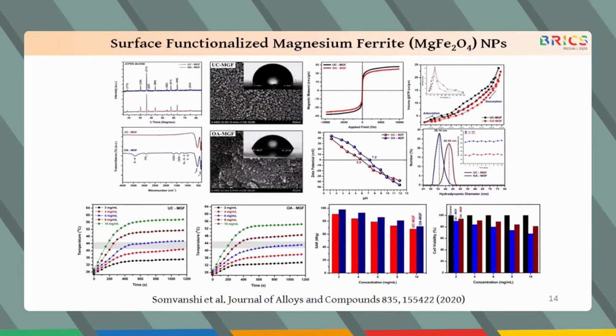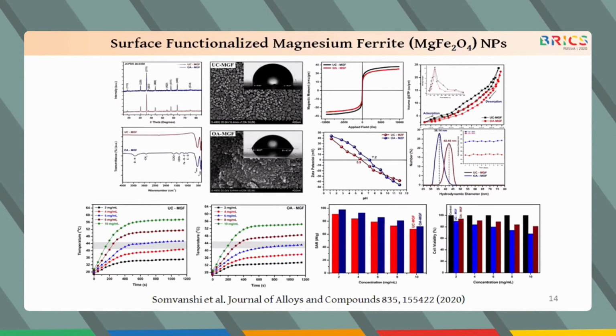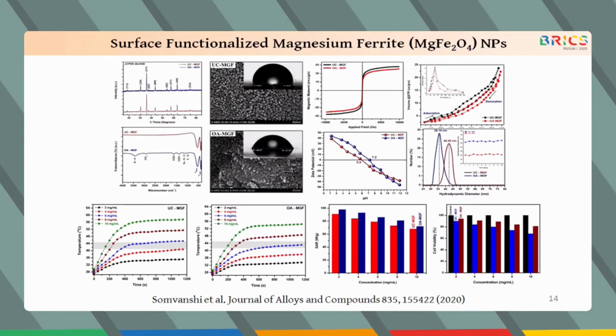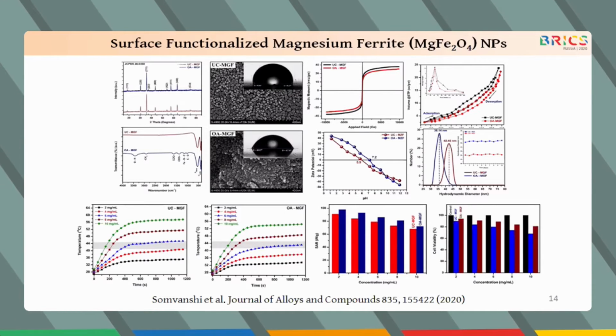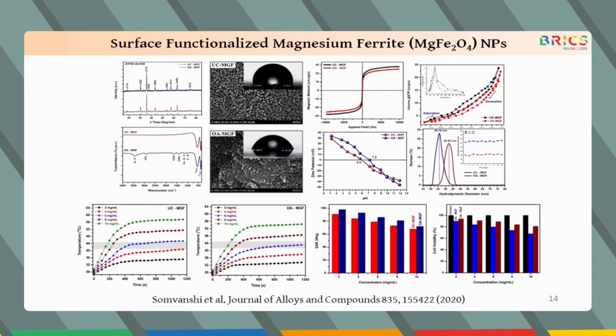Similar to the zinc ferrite, we have prepared magnesium ferrite nanoparticles and functionalized its surface by oleic acid. As compared to zinc ferrite, magnesium ferrite showed enhancement in the heating performance and requires less nanoparticle dosage.